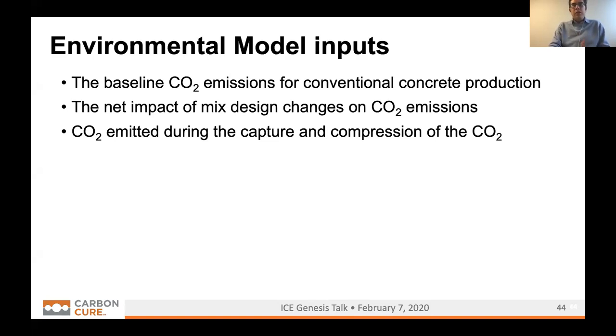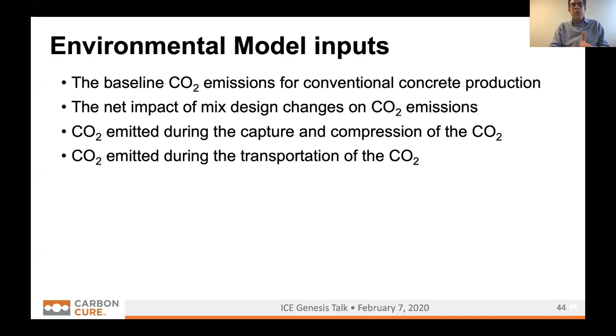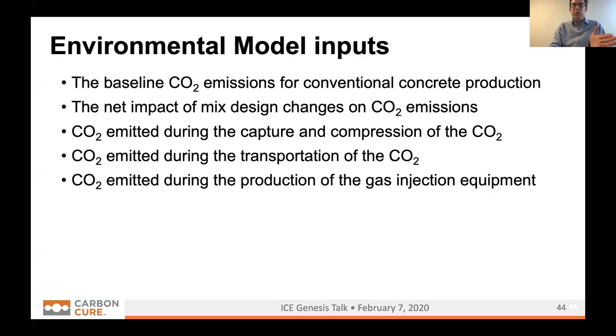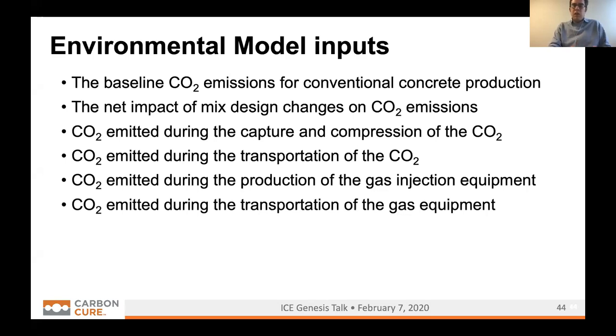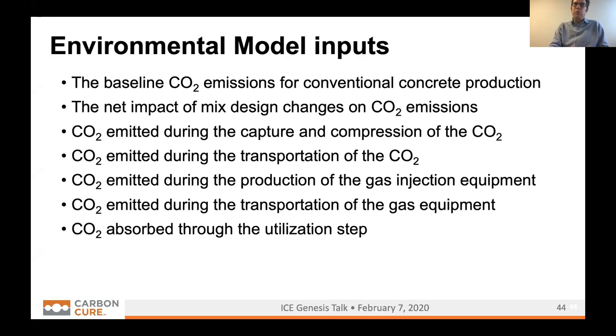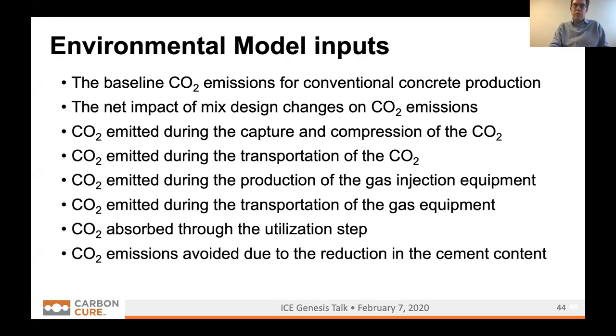We have to know the CO2 that would be emitted during the capture and compression of the CO2, CO2 emitted during transportation of the CO2, emissions during the production of the gas injection equipment, emissions during the transportation of the gas equipment, and CO2 that's directly absorbed in the utilization step. Ultimately, then, we look at the avoided CO2 emissions from the avoided cement content.